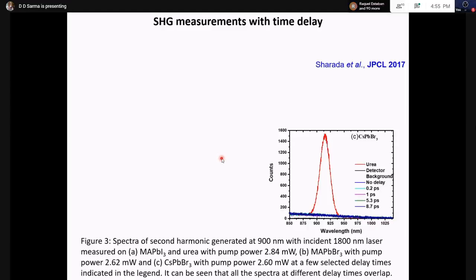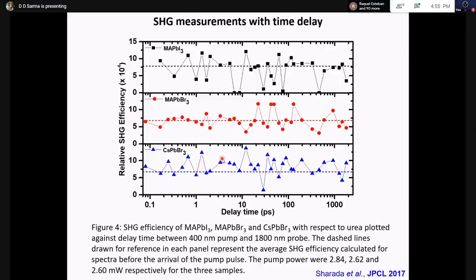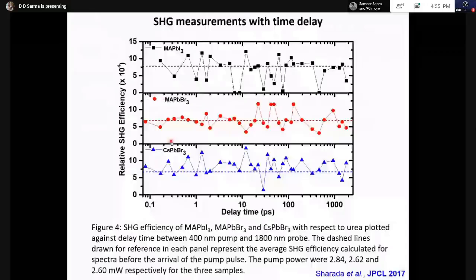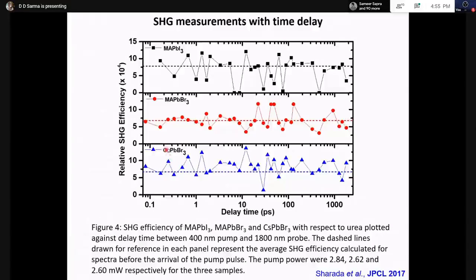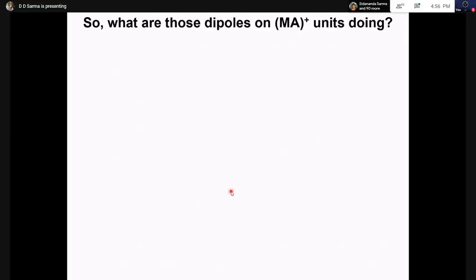I'll give you only the conclusion. We have done this. These are the data that conclude that this is the signal that we get, second harmonic generation, which is essentially the noise. The 0 level is drawn by a dashed line for all these: MAPbI3, MAPbBr3, CsPbBr3. The reason we look at CsPbBr3 is that instead of MA we have put cesium, which has no dipole. So we know what the level of the 0 signal should be, and that provides me the 0 signal. And you can see that all of these are only noise, and there is no second harmonic generation, even transiently. So there is no transient ferroelectricity that is getting generated.